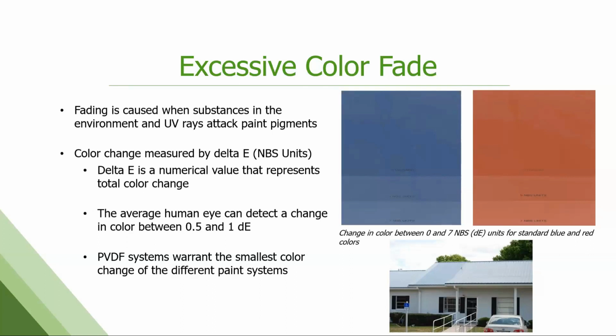There's a couple things that could be going on here. When you have some panels that are performing or fading differently than others, it could be a few things. It could be mixing paint systems. Someone could have intermixed, say, PVDF with a polyester or an SMP with a polyester. It could be that part of these panels were not at the right film thickness when they were made, so they're fading faster. It could be different paint suppliers, right? Blue number 14 from supplier A and supplier B may not be formulated exactly the same, and they may not fade exactly the same. So you don't want to mix suppliers on a building either, because you will get differential performance.